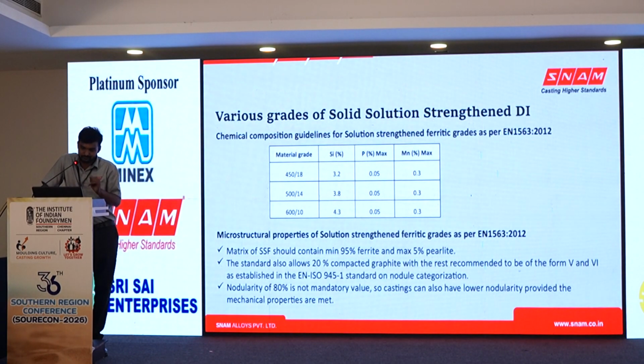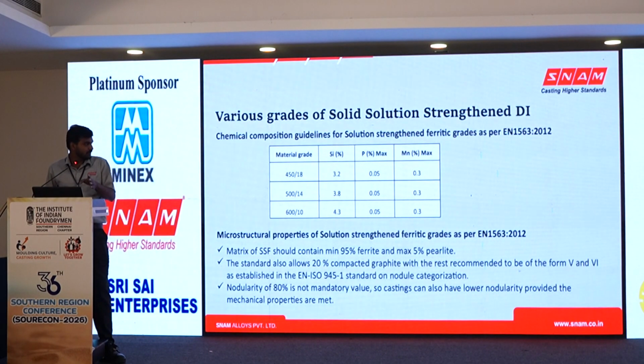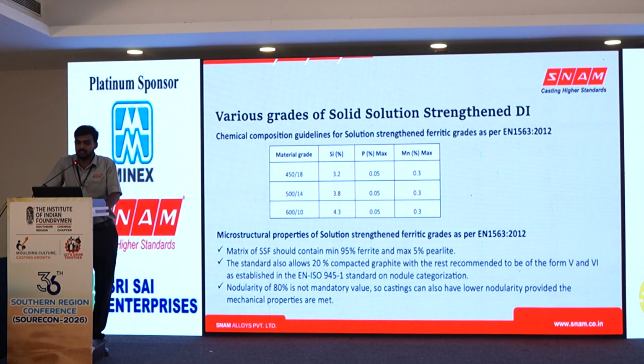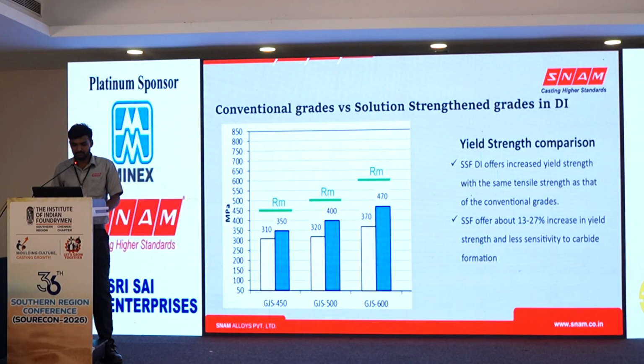Compacted graphite iron is allowed, but the rest it should be recommended to form type 5 or 6 grade nodule category as per established in EN standard ISO 945-1. And also nodularity of 80% is not mandatory. But we should achieve the mechanical properties. If we achieve the mechanical properties, nodularity of 80% is not mandatory.